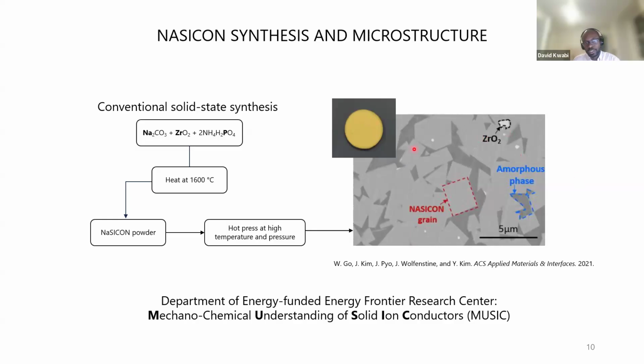But we found out, looking at the microstructure of these materials, that they're extremely heterogeneous. You have regions that have a NaSICON grain, so the crystalline material, but you also have secondary phases. Zirconium oxide is one example of a secondary phase, and you also have amorphous phases in the microstructure as well. So one of the questions that we set out to ask in going about this research is, how do these different phases respond to the aqueous electrolyte while they're actually being cycled in the flow battery?